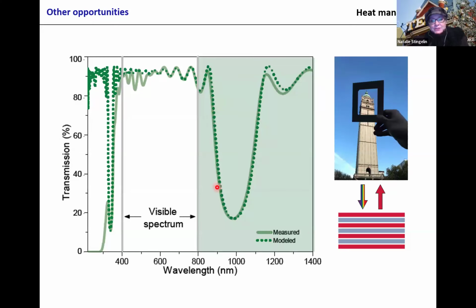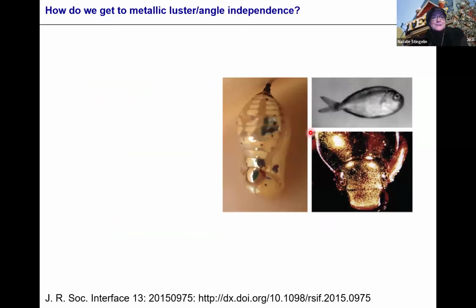So we can make plastic infrared mirrors, plastic heat mirrors. The problem for many applications is the reflection band, the wavelength regime where you have reflection, is relatively narrow. For solar cells, and also buildings etc., you possibly want to reflect all of the infrared, or near infrared at least. This can be done by changing the stacking a bit.